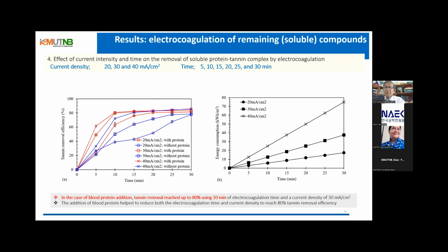This figure shows the energy consumption as a function of the current density and electrolysis time. The system with the addition of blood proteins requires less energy to remove tannins because of the shorter electrolysis time and lower current density. For the system with the addition of blood protein, a tannin removal of around 80% can be achieved with an electrolysis time of 10 minutes and current density of 30 milliamp per square centimeter, consuming about 12.5 kilowatt hour per cubic meter.